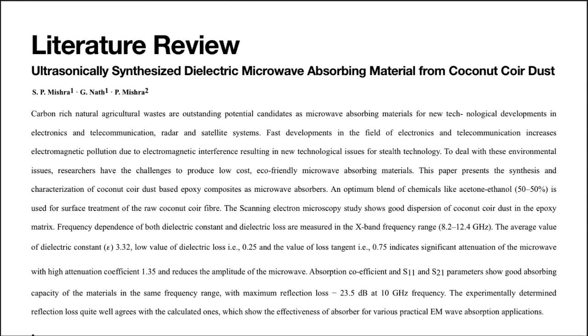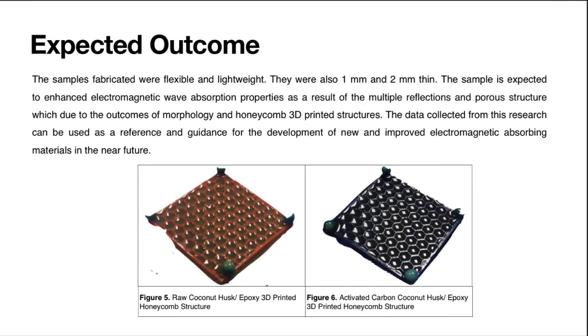Lastly, ultrasonically synthesis dielectric microwave absorbing material from coconut coir dust. This journal shows that the sample with 40% of coconut fiber dust has potential to be used as an alternative material for microwave absorber application compared to other bigger percentage. The samples fabricated were flexible and lightweight. They were also 1 mm and 2 mm thin.